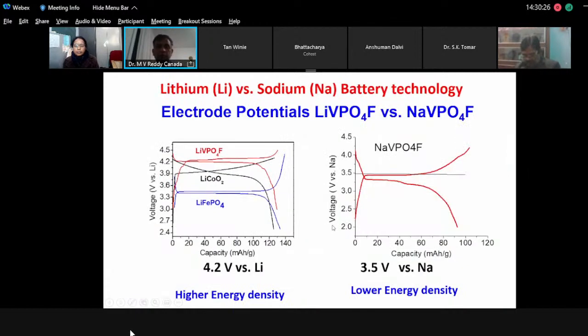So quickly I'll show that almost nearly 4.2 volt versus lithium, for example, 3.5 volt. So although we get lower energy density, practically in terms of cost, I think sodium seems to be almost 20% of the cost we can reduce by replacing lithium with sodium.